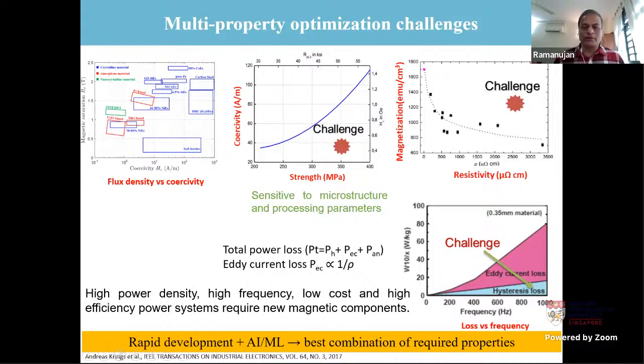There are challenges because, for example, if you increase the strength, the coercivity also increases. If you try to change the magnetization, typically the magnetization is inversely related to the resistivity. So it's difficult to optimize all the properties for a given composition, because some compositions have good magnetic properties, but not good mechanical properties, etc. So what we want to do is to solve this problem using AI in addition to the experimental parts.